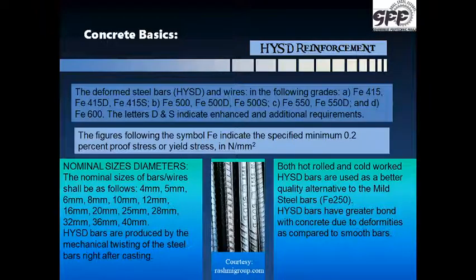The steel bars of Fe415, 415D and 415S have 0.2% proof stress or yield stress as specified as 415 Newton per mm square, and the minimum percentage elongation on the gauge length, that is 5.65 root A, will be 14.5, 18 and 20 respectively for the three bars. Similarly, the values have been defined in IS 1786 for Fe500, Fe500D and Fe500S, and similarly for Fe600 also.